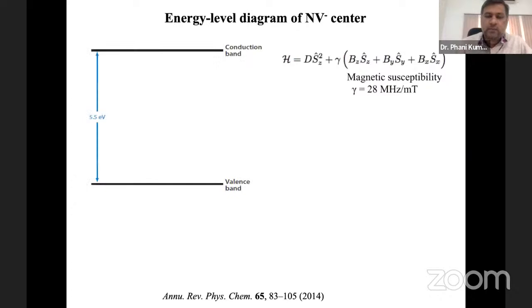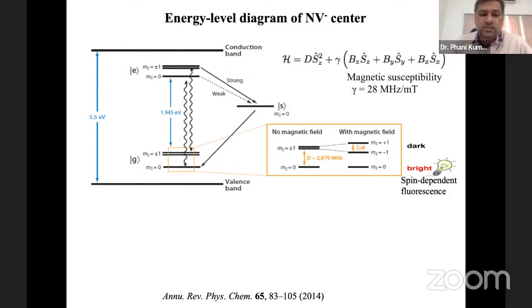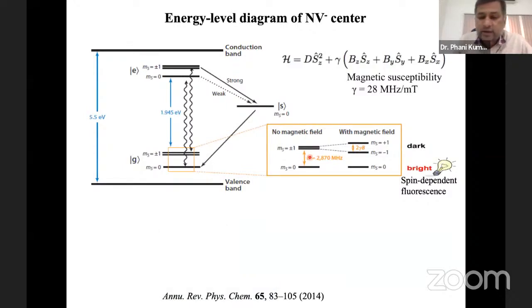So let me start by explaining briefly the energy level diagram of the NV center. We have a diamond, which is a very large band gap insulator. It has a band gap of around 5.5 electron volts. And the energy states of this NV center are within this band gap. You have this ground state manifold, which is labeled by G, and we have the excited state manifold. These are the orbital states. And within each manifold, we also have these spin sublevels because this NV center has a spin of 1. At zero magnetic field, the MS equal plus or minus 1 sublevels are separated from the MS equal to 0 state by this 2.87 gigahertz, and this is due to the spin-spin interactions. When you apply a finite magnetic field, the MS equal plus or minus 1 levels split, and so we can measure this Zeeman effect using optically detected electron spin resonance techniques.